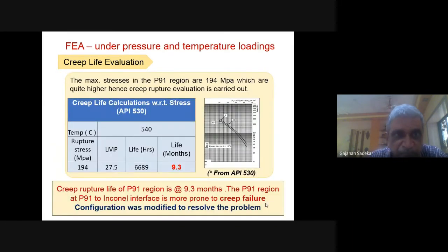So what we did, we actually studied the alloy steel part of it. The maximum stress in the P91 region is 194 MPa, which is quite high. Hence, creep rupture evaluation is carried out. There we looked at the interface between the Inconel and the alloy steel. After evaluation we found the creep life is only 9.3 months. The P91 region at the P91 to Inconel interface is more prone to creep failure. And that's what happens.